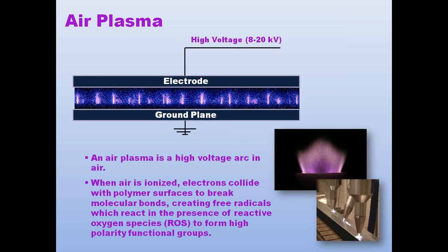The top indication is a reflection of a planar approach whereby we are using high voltage, between 8 to 20 kilovolts, building up voltage in that anode or top electrode until the point where we are able to create an avalanche of electrons to the surface of the material, to a ground plane. What is interesting about the profile of that discharge is that those micro discharges will actually arc to the same spot on the ground plane over time. And this is a memory effect. There's a lot of detail behind this, but essentially those discharges are random, but at the same time will be in place relative to their discharge path to the cathode.